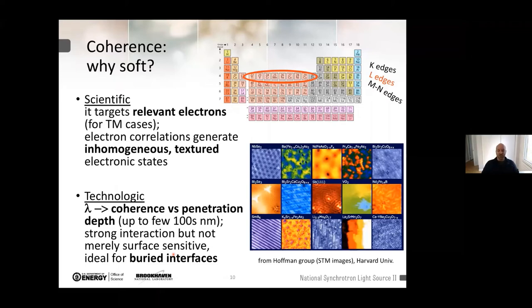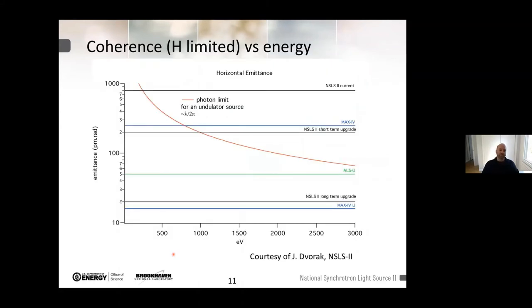It falls in the happy spot between interacting strongly enough to bring very strong information out of materials, let's compare to neutrons, for example, which is the opposite extreme, and not interacting so strongly as to be confined only to the top layer of materials, but being bulk enough that oxidation properties happening at the surface can impact the signal, but not necessarily and not too much. So we are just in an ideal spot to study, for example, buried interfaces.